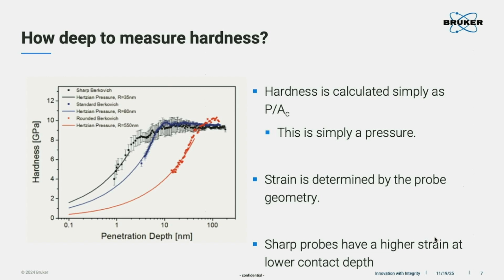So this is another thing we need to consider. Just as I mentioned, different probes have different stress concentration. The sharper the probe, the higher the concentration is, right? So if we look at this, these are just 3 different probes. One is 35 nanometer radius, another one is 80, another one is much larger, more than 500 nanometer.